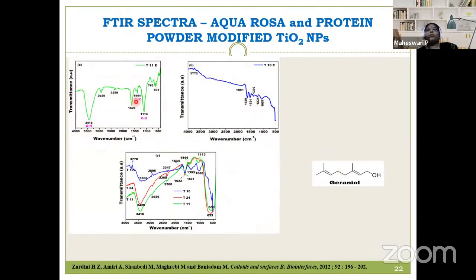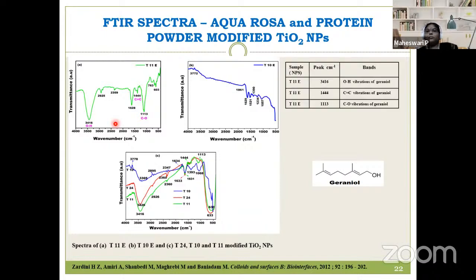and this is a spectra. This is the spectra for the aqua rosa extract alone. And this is the FTIR spectrum for the protein powder extract alone. So you can see here, at 3416, we can see the OH vibration of the geraniol compound. And at 1444, we see the C double bond C vibration of geraniol. And similarly, the CO vibration of geraniol is found around 1130. So here we have made out where the geraniol compound is.